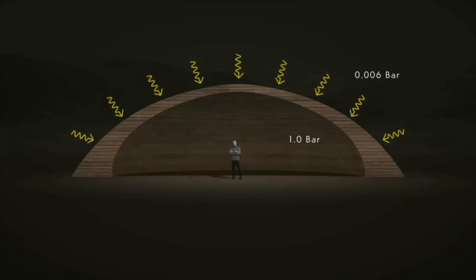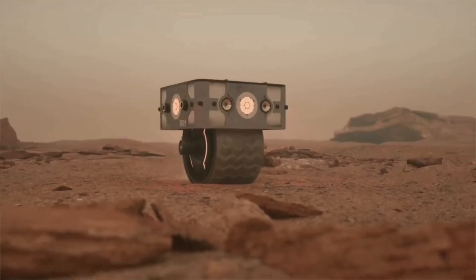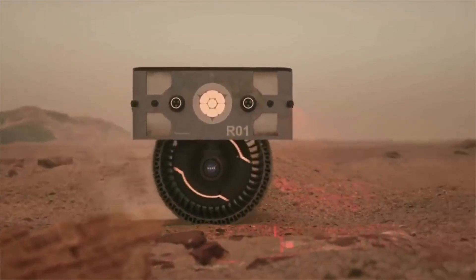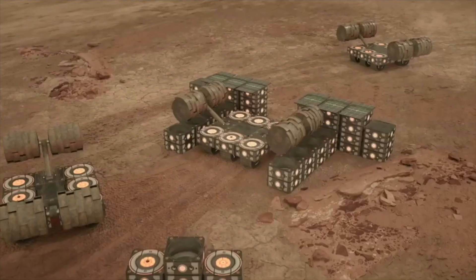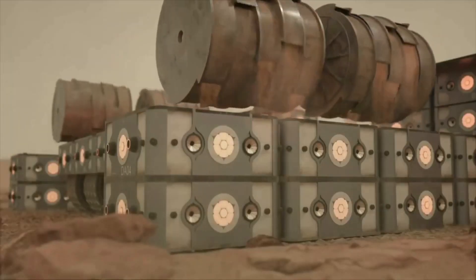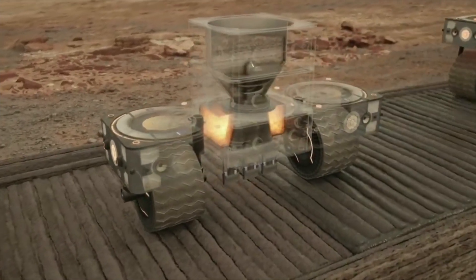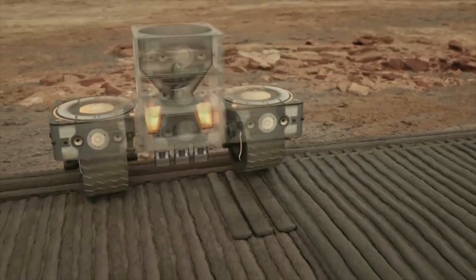But the atmosphere of Mars is sufficient to make sulfur concrete. So the question is, how shall we make sulfur concrete on Mars? According to current research findings, the basic idea is to heat sulfur to about 240 degrees centigrade so that it becomes liquid. Thereafter, we mix it with Martian soil, which acts as an aggregate, and then we let it cool. The sulfur solidifies, and as it does so, it binds with the aggregate, thus creating what we are calling Martian concrete.